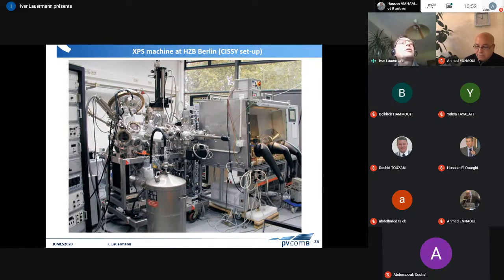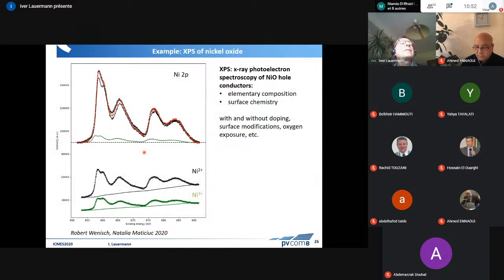This is a picture of my laboratory with the machine. And what we get is a spectrum like this. For example, if we look at nickel oxide, which is a material that we use, the nickel 2p spectrum. And here we are interested in the ratio between nickel 2+ and nickel 3+. So we have to deconvolute the spectrum to find out what the composition of the sample is. And this is crucial for the p-conductivity, and for the conductivity and also for the transparency as a whole.